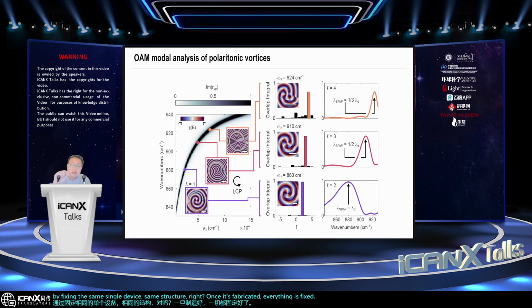Well, with just a very small change of the frequency, you can see the OAM is migrating. For example, in this case, when you change the frequency, the OAM changes from 2 to 4. It's just by slightly changing the frequency. As I mentioned, this is given by the strong dispersion of this material.